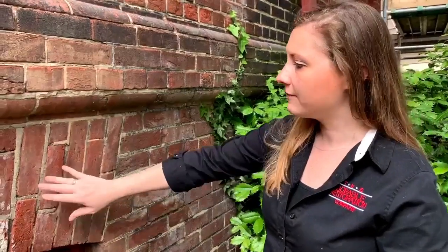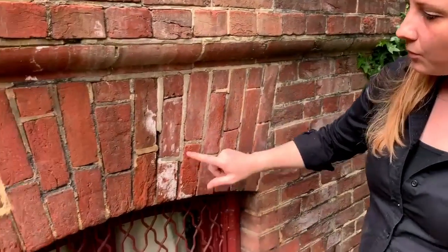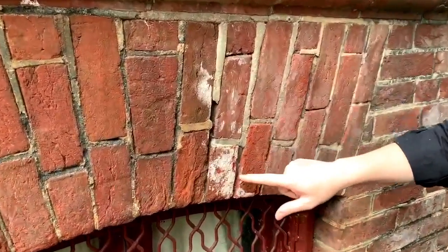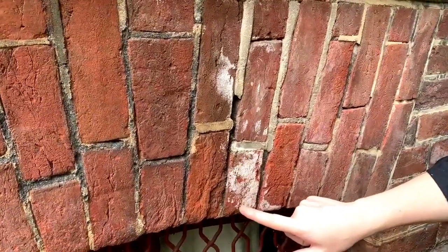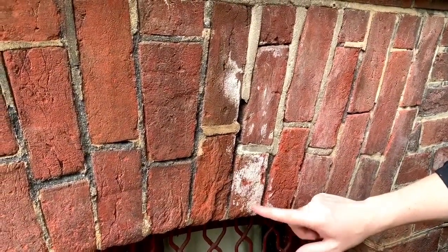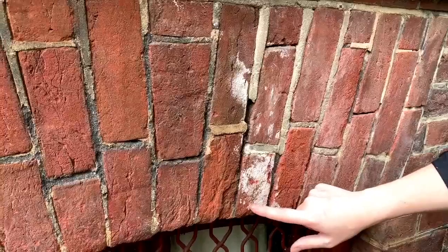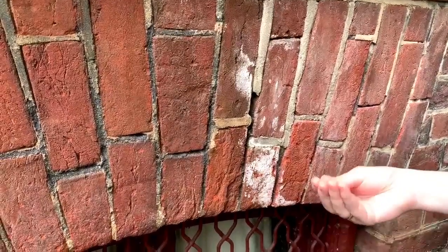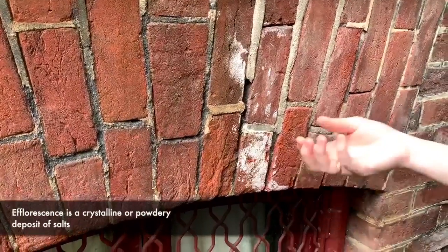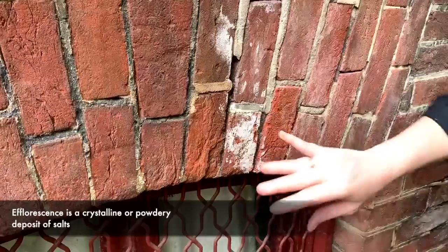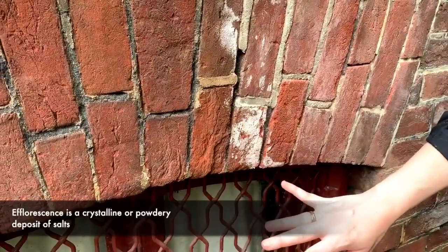If the mortar that is used is improper, such as a Portland cement-based mortar, which is a much more modern material, what you're going to have is something like this, where the water is escaping through the brick. We see evidence of this here because the salts that are in the water are efflorescence here on the exterior of the brick. That's just salt that was in the water that, as it leaves the brick, remains on the surface.